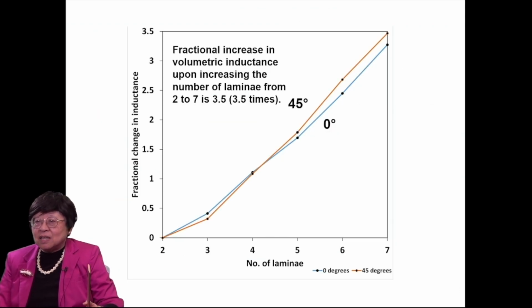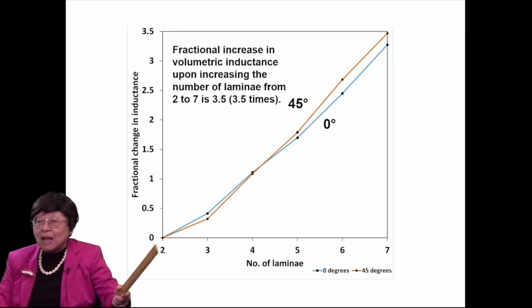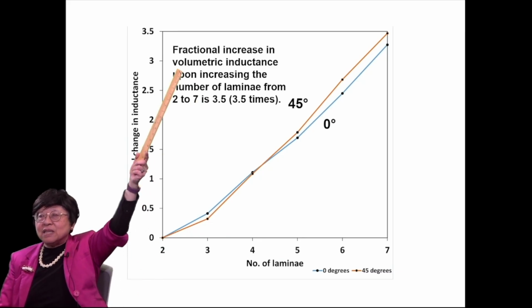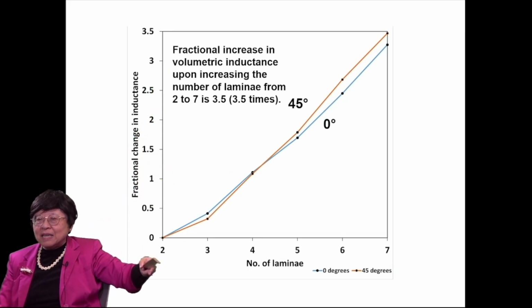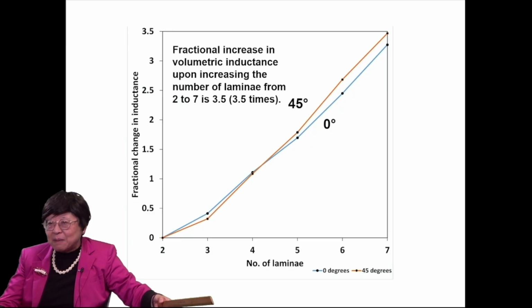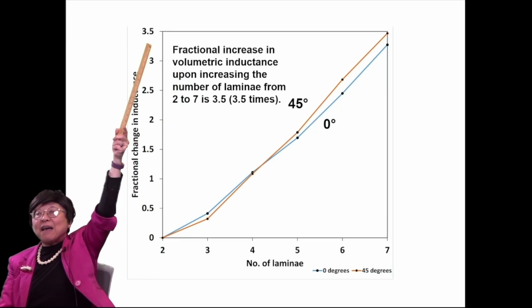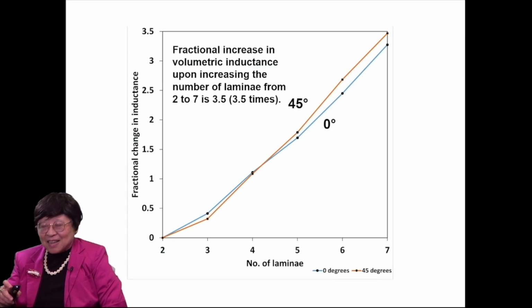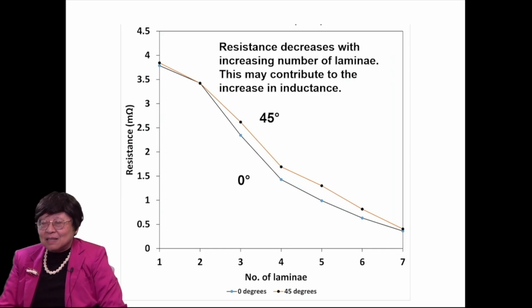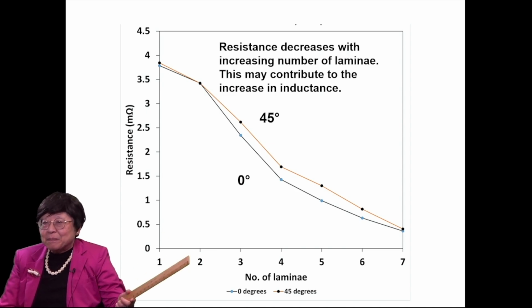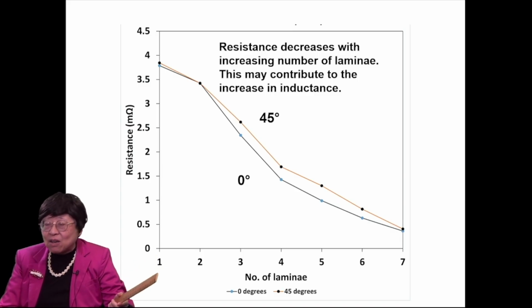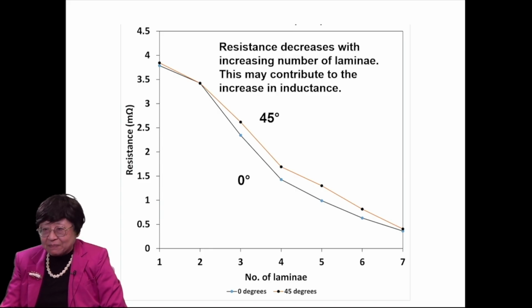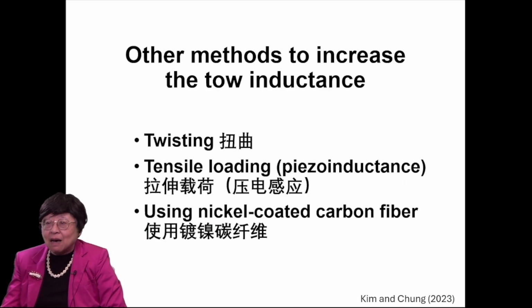And this is the fractional change in inductance relative to the case of 2 laminae. And you can see that this fractional increase when you go from 2 laminae to 7 laminae, that is 3.5 times, gives you 3.5 times the change in inductance. So the two kind of jive. Okay. The resistance, on the other hand, decreases with the increasing number of laminae. That's expected. But this decrease in the resistance with the increasing number of laminae may contribute to the increase in inductance. Okay. The resistance and inductance are not independent of one another.